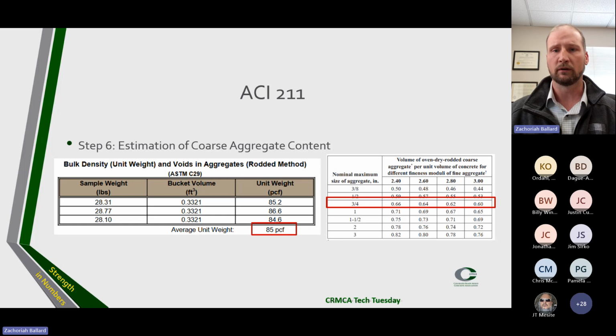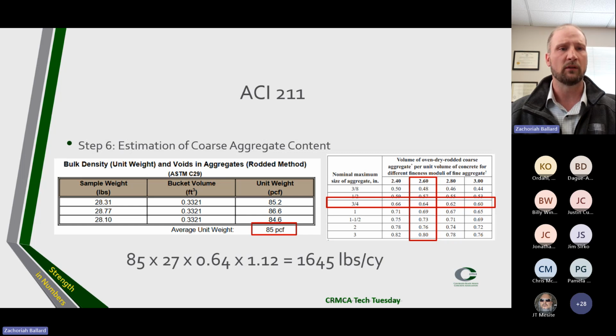This value is multiplied by 27, converted to a dry unit weight, multiplying by a bulk volume. We're then going to convert that to an equivalent SSD weight by multiplying by 1 plus the absorption. So we use these values here, 0.64. So all of that put together, we use our 85 pounds per cubic foot, multiplied by 27, multiplied by that 0.64, multiplied by a factor for our absorption, gives us our starting aggregate content for our mix. This is in pounds per cubic yard now.